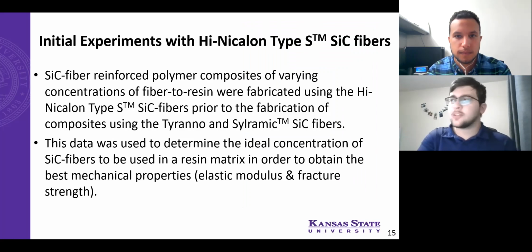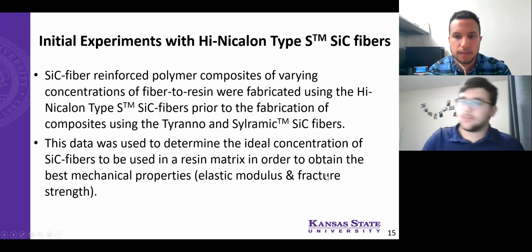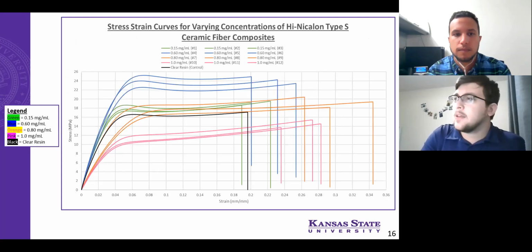So we did some initial experiments with the Hi-Nicalon Type S fibers just to determine the concentration of fibers to resin that we wanted to use. Once we created these samples and did some tensile testing, we used this as the concentration for the fibers in our comparison later. So here's the data from that.